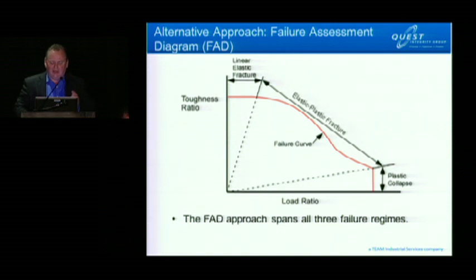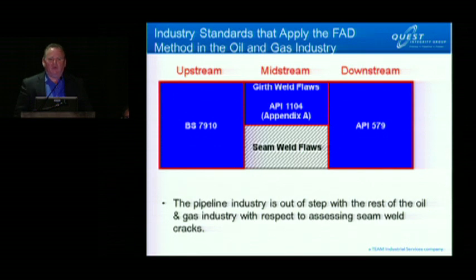You have the linear elastic, elastic plastic, and the plastic collapse embedded in this model. Now, who's using this approach? Well, if you look at oil and gas, the upstream oil production, especially offshore, is characterized by British Standard 7910. At the downstream side, in the refining world, they use API 579. And midstream pipelines, for girth weld flaws in new construction, API 1104 also has a failure assessment diagram method.